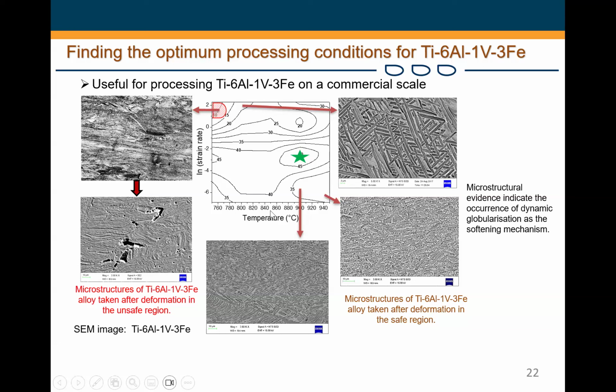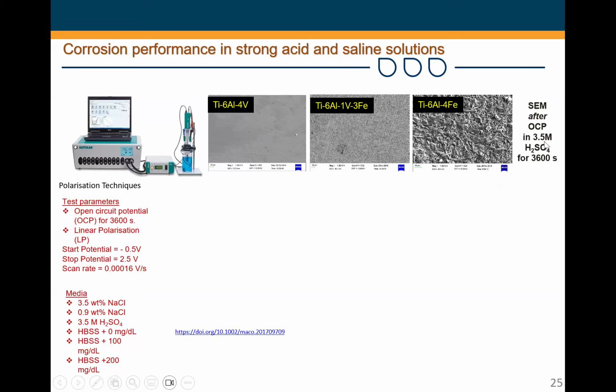We use basically electrochemical techniques, which is open circuit potential and linear polarization, to try to understand what effect iron is contributing in terms of corrosion performance. And we were able to see that if you just do OCP, and this is an alloy where you've totally removed the vanadium, and here you have partial replacement, in very strong reducing sulfuric acid, you can see we have corrosion products formed here, which is telling you maybe it's a bad idea to replace vanadium with iron. But if you do the partial substitution, you don't have this much corrosion products. And you can see for it does seem like nothing happened, basically.